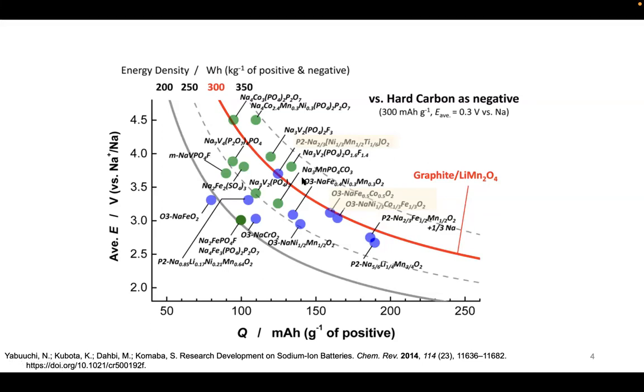So you have here P2, sodium 2/3, nickel, manganese, titanium oxide. You also see some sodium cobalt oxide with half substitution with iron. So there are some similarities, but the chemistry is actually quite different, and how these compounds restructure upon sodiation and desodiation are quite different than that of lithium ion batteries, right? So that's what we'll focus on, how are they actually different? And how does that benefit and also limit the use of sodium ion batteries?